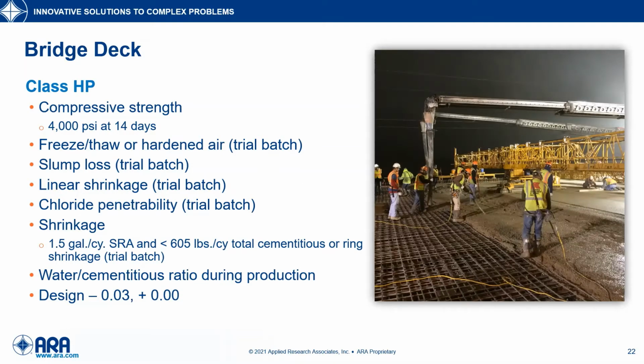We use the Class HP high performance concrete mixture for bridge decks. It's designed for 4,000 PSI at 14 days. It requires freeze-thaw or hardened air, a slump loss test, linear shrinkage, ring shrinkage, chloride penetrability, and then has some water cementitious ratio tolerances during production.